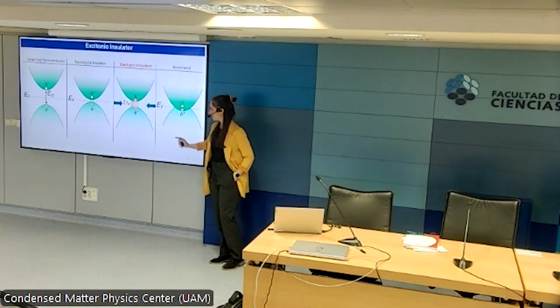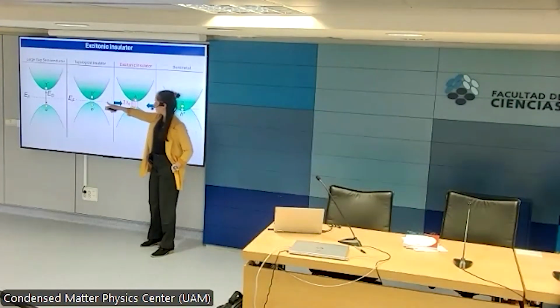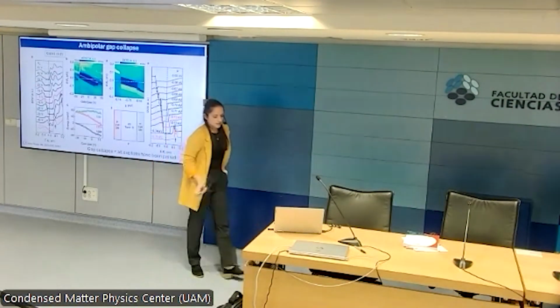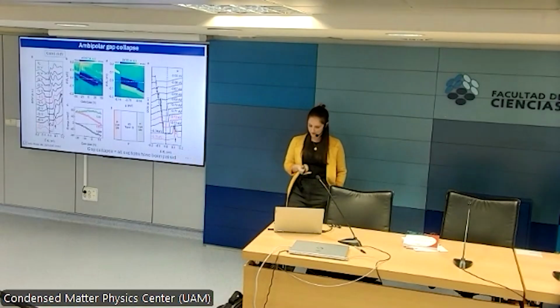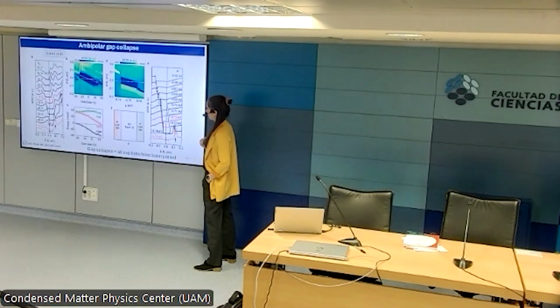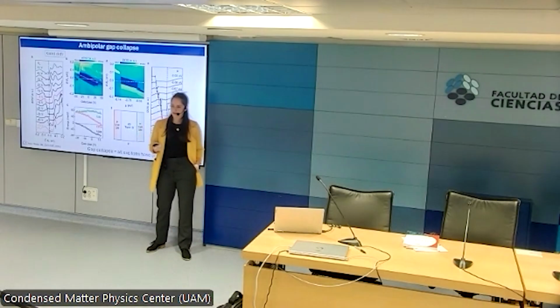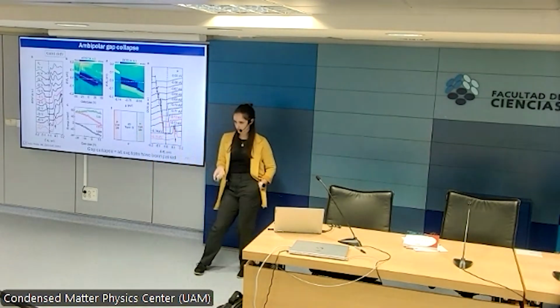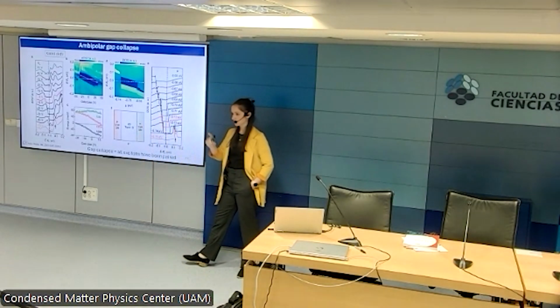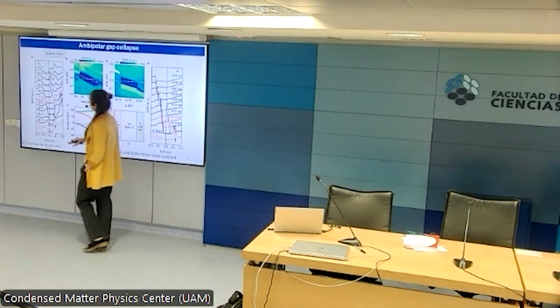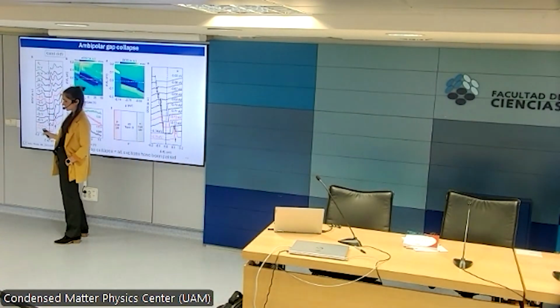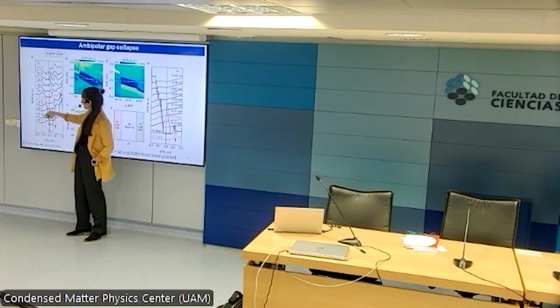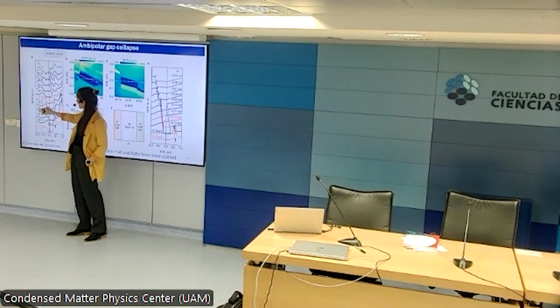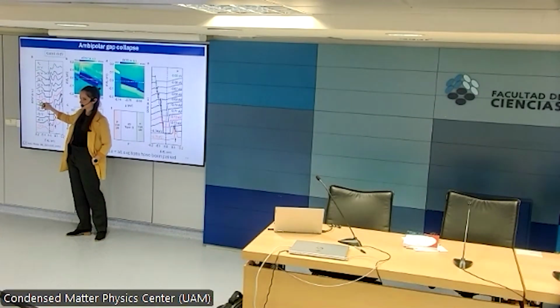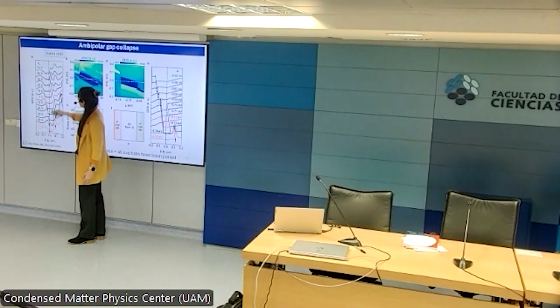Further proof that tungsten ditelluride is indeed in this state came a bit later in 2024, from the group of Ben Weber. I'm going to try and explain to you this very dense figure. They again grow this material, tungsten ditelluride, via molecular beam epitaxy, on a system that they can gate, so apply a bias to. And they look at the local density of states as a function of the bias applied to your system. So the red curve here is your density of states at 0 bias, which is your standard density of states. And you can see that there's a hard band gap of about 60 meV. So the density of states reaches exactly 0 here. And then they start gating the system.